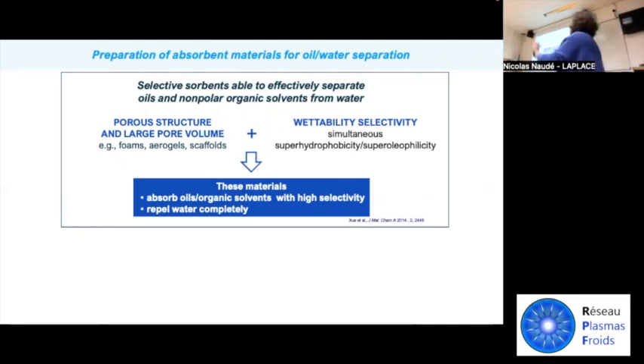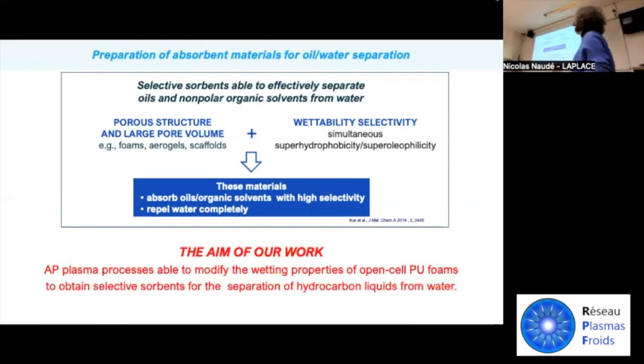That is, selective sorbents able to effectively separate oils and non-polar organic solvents from water need to combine a porous structure and large pore volume, such as in case of a foam, and wettability selectivity. In this way, we can obtain materials that are able to selectively absorb the oils or organic solvents with high selectivity from water, while repelling water completely. And so the aim of our work has been the optimization of plasma processes able to modify the wetting properties of open cell polyurethane foam to obtain selective absorbents for the separation of hydrocarbon liquids from water.